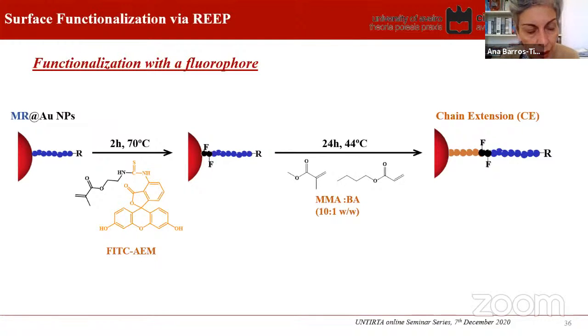So we try to take advantage of this possibility of Raft polymerization to co-polymerize the macro Raft agent with another monomer which had been modified with FITC, which is a well-known fluorophore. So for that, we had to react this macro Raft agent, which was already anchored or absorbed at the gold nanoparticles, and graft this other monomer